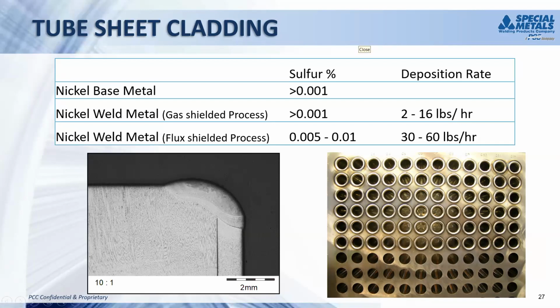You could take one option of using a gas shielded process such as TIG, and you're going to end up with the same amount of sulfur you started with in the wire, essentially. That's where you see the nickel base metal with the sulfur less than 0.001. The weld metal from a gas process would also be around 0.001%. One of the downsides is your deposition rate could be anywhere from as low as 2 pounds an hour to maybe, if you're really pushing a hot wire process, up towards 16 pounds an hour. Whereas with strip cladding, you can be as high as 30 to 60 pounds an hour. So we can be much quicker.